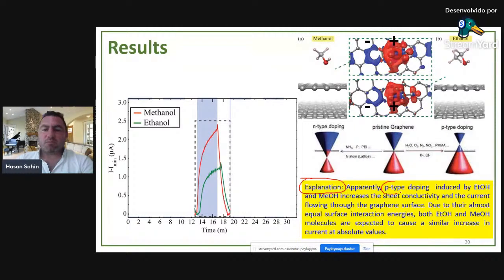P-type doping means that you are removing some electrons from the graphene surface, and at these domains you are removing or repelling some electrons from the surface. So both ethanol and methanol increase the sheet conductivity and the current flowing through the graphene surface. Because of doping, you are increasing the sheet conductivity. And if the sheet conductivity is increasing, here you see the increase in the base current because of doping.